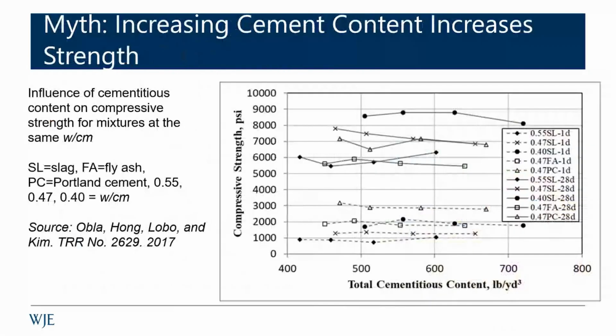There's a myth that exists that increasing cement content increases strength. You see it embedded in specifications time and time again. You see it embedded within the NRMCA benchmarking for the carbon footprint of concrete. But this is data from NRMCA, and it just basically shows that strength-wise, you're not going to see any marked difference with increasing cement as long as water cement ratio is maintained. So what we need to do, focus on the water cement ratio and keep that the same.